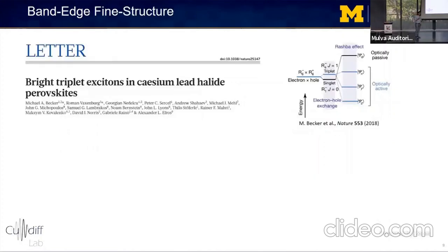So the exciton fine structure in perovskite nanocrystals is one of their most discussed properties. And it all started with this Nature paper in 2018, which presented evidence that the exciton band edge in these perovskite nanocrystals is composed of a dark state and 3 non-degenerate bright states. And what's so special here is that the dark state is actually highest in energy, whereas in other materials, the dark state is always lowest in energy due to the electron-hole exchange interaction.